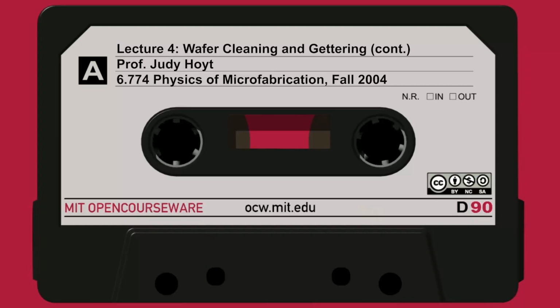So whatever oxygen was in the top 10 microns can go out. Oxygen buried deeper below that at this high temperature can't make it because it can't diffuse. It doesn't have enough time to diffuse that amount of distance. So one of the first steps people use for doing intrinsic gettering is sometimes a high temperature step to create this denuded zone or to grow an epitaxial silicon layer.